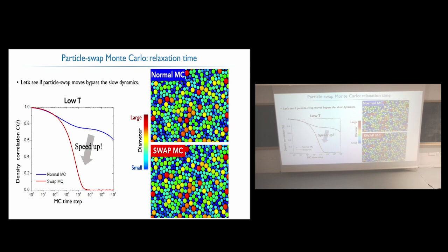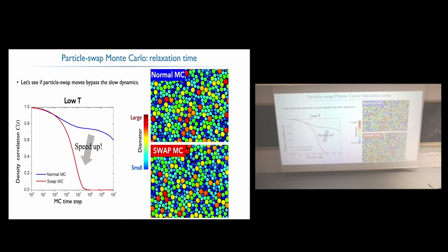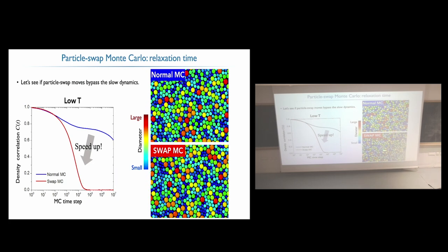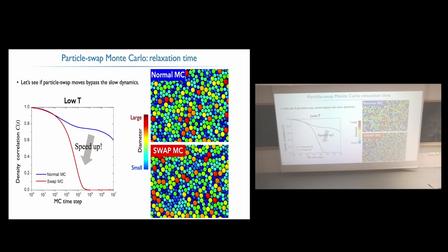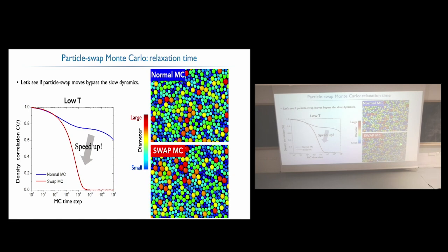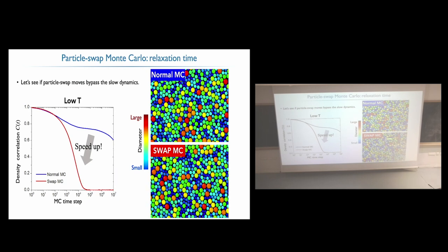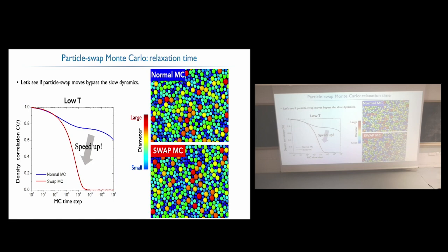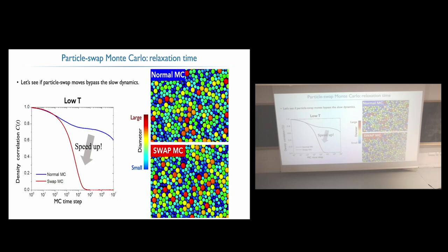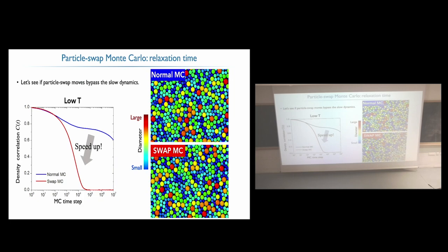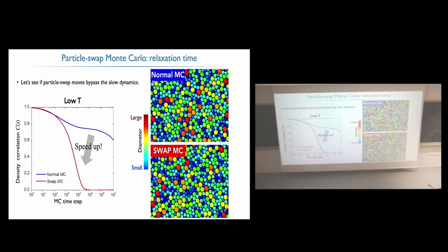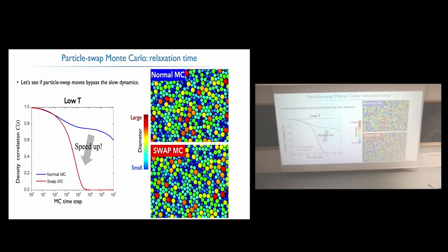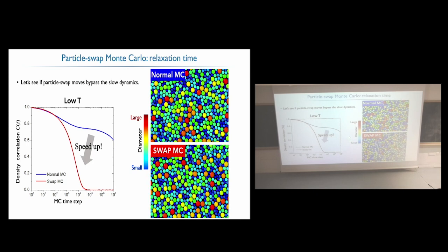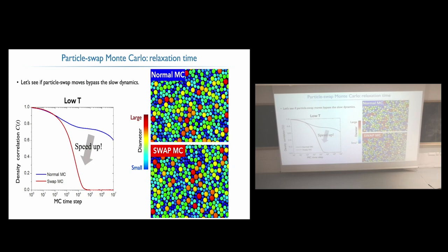If you turn on this very small thing, which is doing the swap, this is what happens. Sorry, I hope you don't have epilepsy. You can see that it makes a big change at least. The particles now can change their size, and this really relaxes the structure much more easily. At the same temperature, you switch on the swap, and then maybe the relaxation time would be around here, and now it's orders of magnitude faster than before.